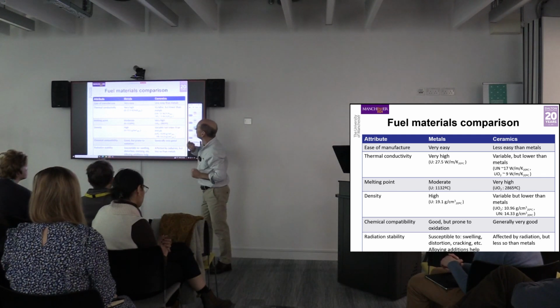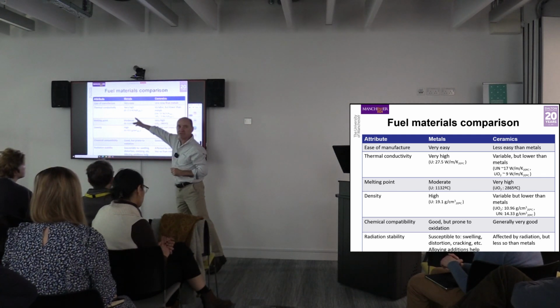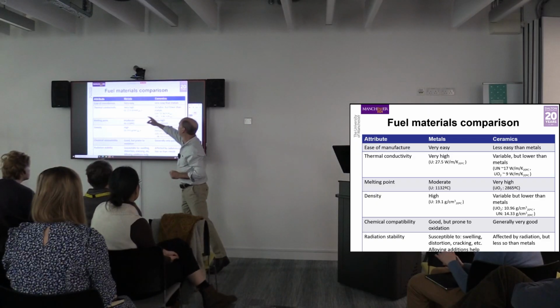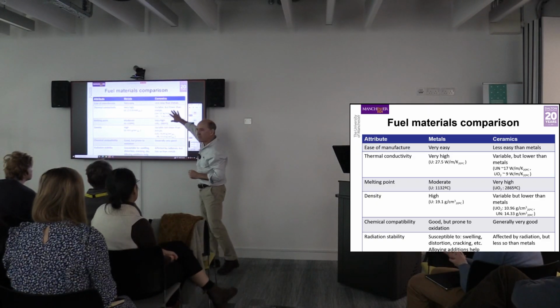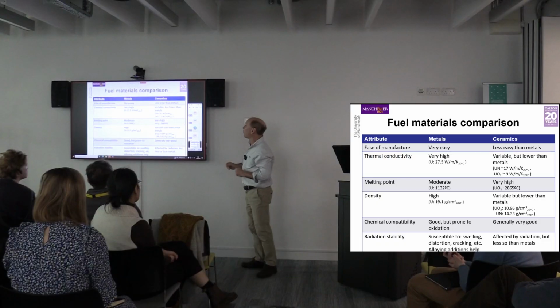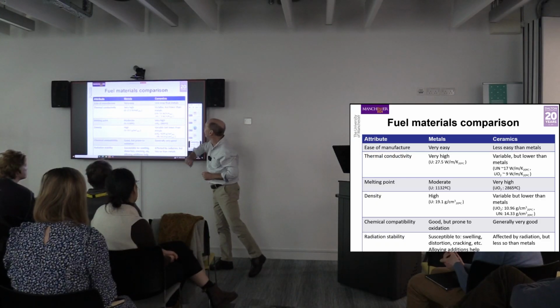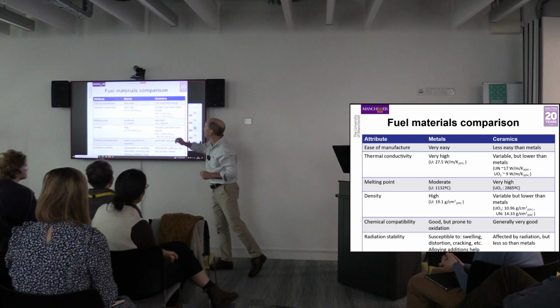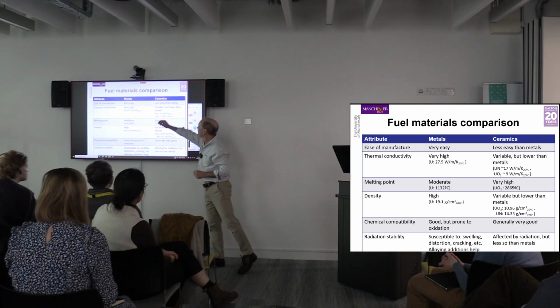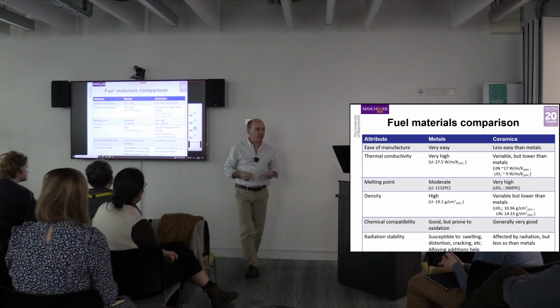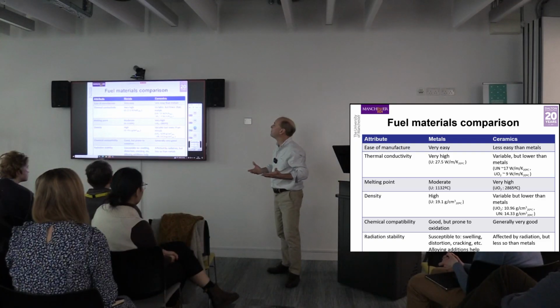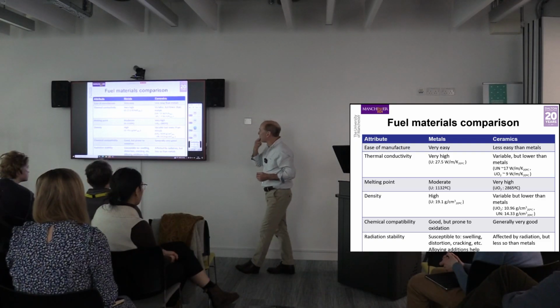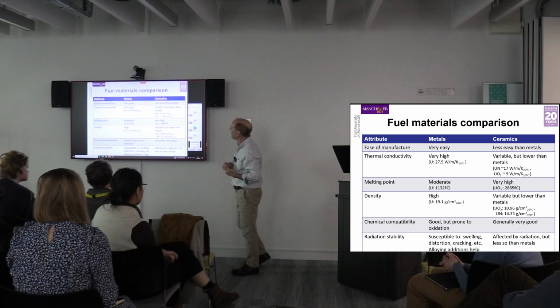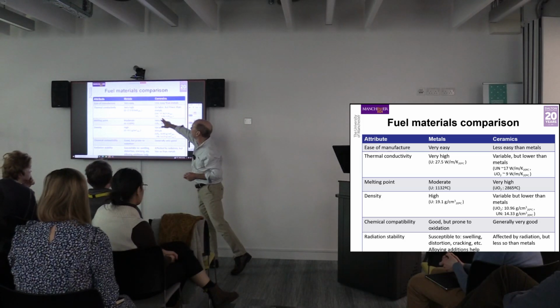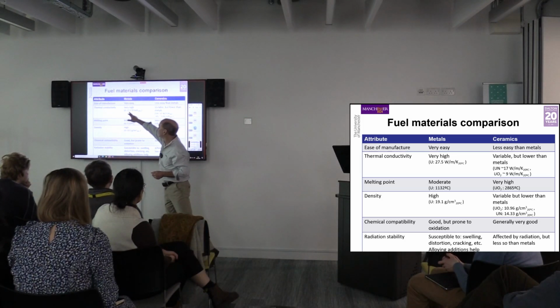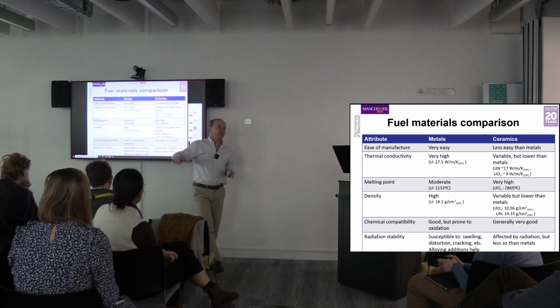How, therefore, do they compare? Well, metals, very conductive, of course they are. Very, very conductive compared with ceramics. Ceramics, really variable. Some of them are quite good. Uranium nitride, for example, at 20 degrees C, has a thermal conductivity of around about 17 watts per metre per K. The units are fairly irrelevant here. What matters is the difference between them. Uranium dioxide down at 9, so compare that against the metal itself, which is almost 28.